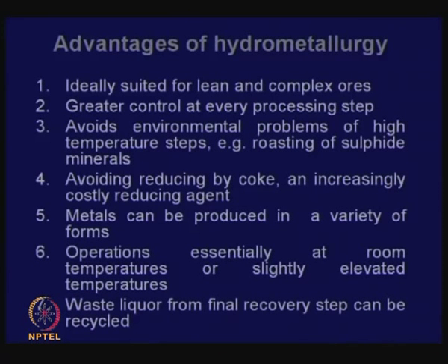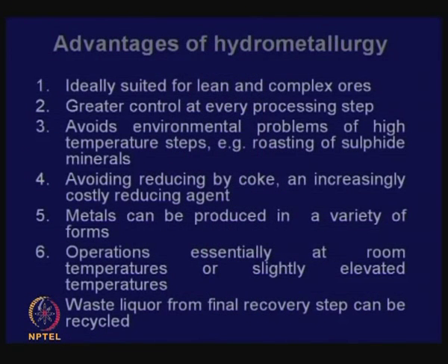Then another advantage with hydrometallurgy is, because of the control you have on reagents, and you can have additives, you can have catalysts, metals can be produced in a variety of forms. You can produce sheets of metal, you can produce powders of metal, you can even produce powders with particular shapes of particles. These have been achieved in hydrometallurgical operations. And since operations essentially are at room temperature or slightly elevated temperatures, things become much more convenient to handle, and the waste liquor from the final recovery step can often be recycled, means you are using some reagents which can be regenerated. Now, these are the advantages,